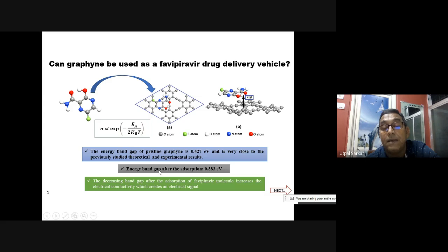And the energy gap is lowering after the adsorption. That means when it is lowering, its conductivity is increasing. That means by simply measuring the conductivity, that means current or something, you can sense it. It can be used as a sensor for the favipiravir molecule by analyzing the conductivity of the whole system. And this decreased band gap after adsorption increases the electrical conductivity because the band gap is lowering. So e to the power minus E by kT, it is proportional to this.